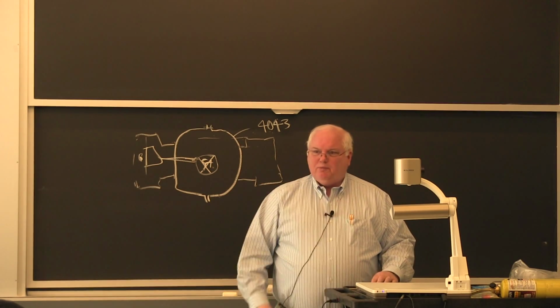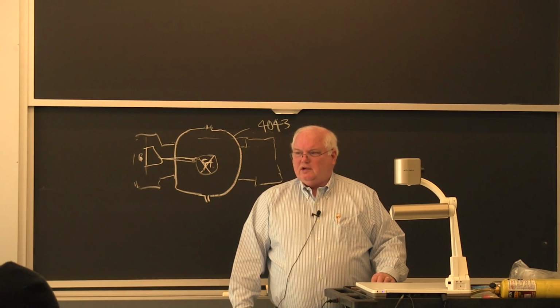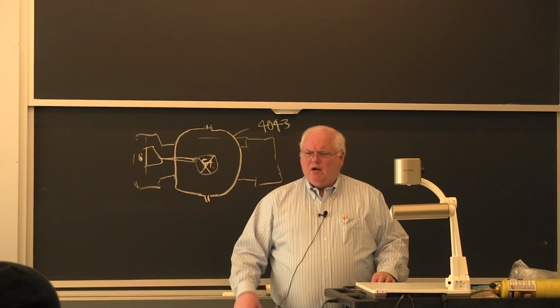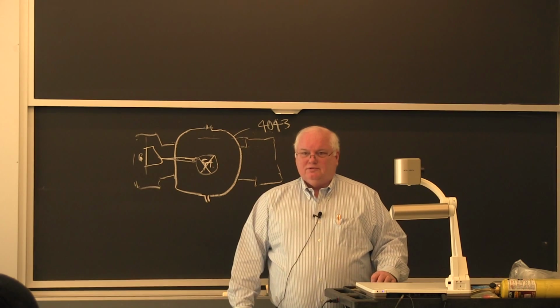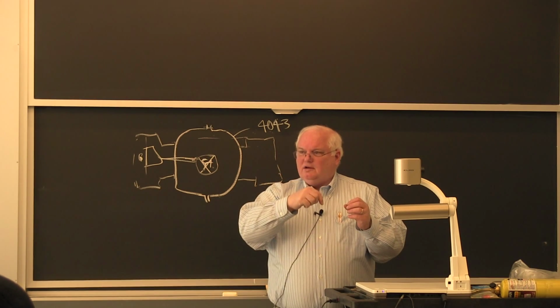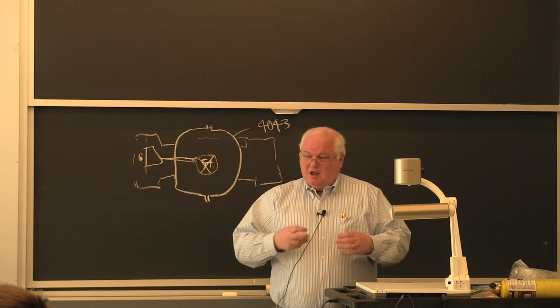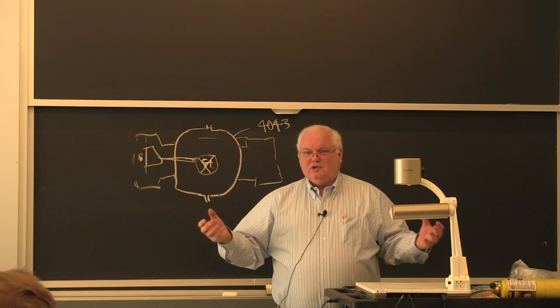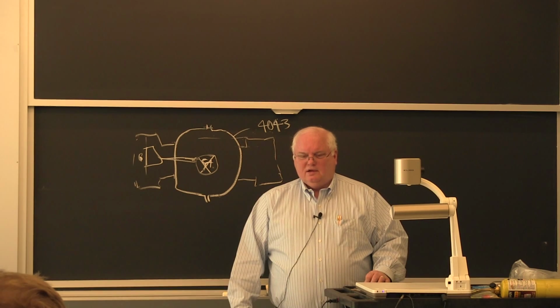I said, what you need is a composite. I said, it's too bad you can't use aluminum for medical instruments. He says, why not? Well, I thought, you know, they might have some problems. He said, we make lots of instruments out of aluminum. I said, you do? Then you ought to use anodized aluminum, because in anodized aluminum you get a top surface that is an insulator with no free electrons, aluminum oxide, which absorbs lots of energy, and then you get the aluminum underneath, which has high thermal conductivity, which will diffuse the heat away. Okay? He says, oh. He says, how do we test that?